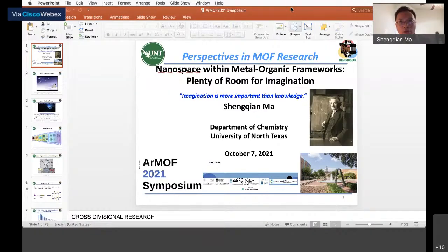We haven't done too much pure gas-solid phase reaction. I think this is definitely one of the directions we are exploring. We don't have this set up in our lab, so that's why we focus on liquids. I'm pretty sure it's going to work, particularly for some very challenging reactions. Of course, one thing I'd like to point out: you cannot go beyond 300 or 350 degrees. There's no way you can do a reaction like zeolite oil cracking at over 500 to 700, because the MOF is going to collapse or carbonize. But below 200 degrees C, for some of them like the MIL series and zirconium, they're okay.